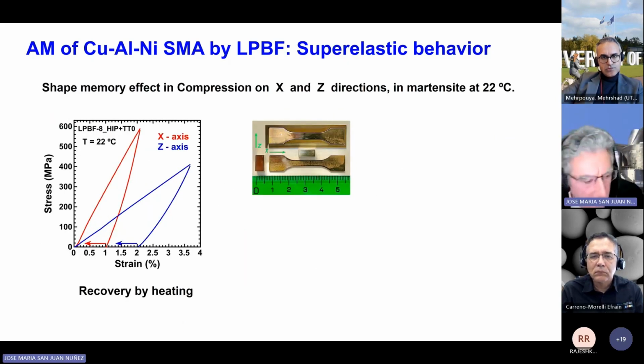This effect is also seen in martensite, because if we test this material at room temperature, at 20 degrees centigrade, then the material is in martensite. So when we apply the compression in the parallel direction and in the transversal direction, we can get a much higher strain in this Z axis. And as we are in martensite, there is some important residual strain that is recovered by heating because of the shape memory effect. This test corresponds to the sample cut in the transversal direction, and this blue corresponds to the cut parallel to the building direction.